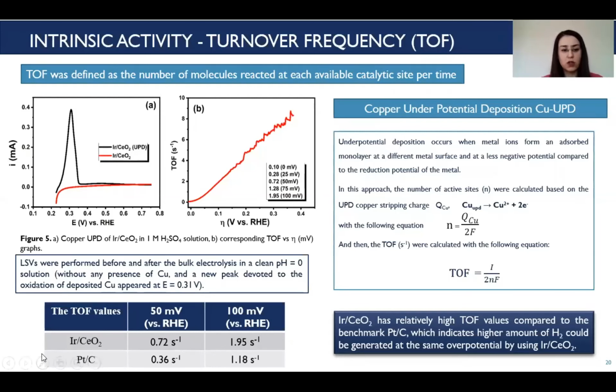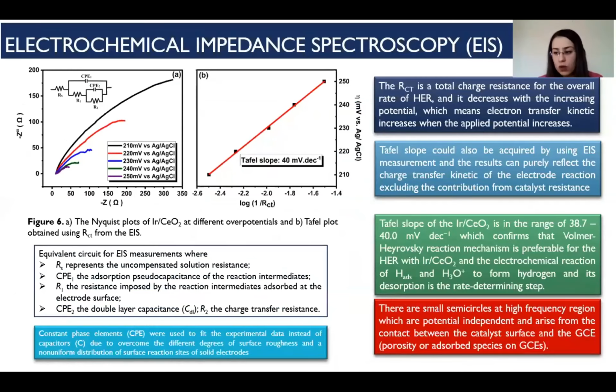After the calculation, iridium ceria shows higher turnover frequency values compared to the benchmark platinum carbon electrode, which indicates a higher amount of hydrogen gas could be generated at the same overpotential by using the iridium ceria catalyst. Also, the electrochemical activity of the iridium ceria was studied by electrochemical impedance spectroscopy. The charge transfer resistance is a total charge resistance for the overall rate of the hydrogen evolution reaction and it decreases with increasing potential, which means electron transfer kinetics increase when the applied potential increases.